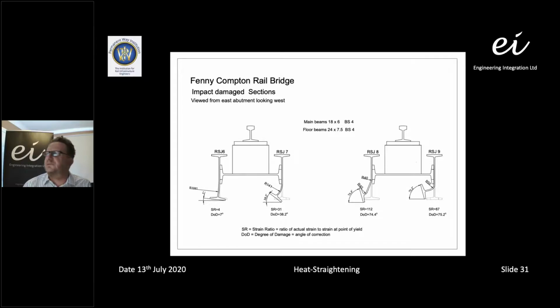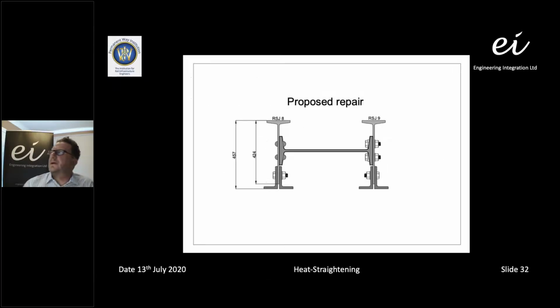So we're taking quite a conservative approach at the moment, but we hope to do some more trials to allow us to understand whether we can actually take the strain ratios beyond 50 or deal with structures that have strain ratios beyond 50 within the UK, and demonstrate that through research and development. That would be the typical repair that we'd be looking for on this type of girder. Because of the extreme strain ratios that were shown in the earlier slide, we would cut the bottom flange off effectively, and then we'd replace that with back-to-back angles, and we'd use heat straightening to straighten the web. So it'd be a combination of techniques to actually deliver the remediation.